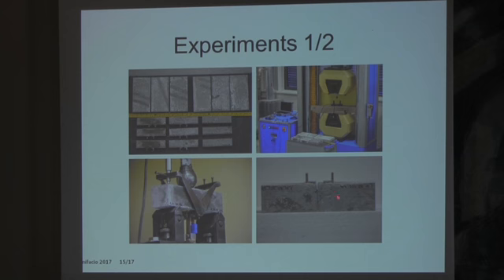Here there is the initial notch, and under the initial notch there is an inclusion. One inclusion, 80 by 8 millimeters, along the whole width and thickness of the specimen, and we now focus on crack propagation along this individual inclusion. This experiment was performed with a steel inclusion because we would like to know the behavior, and the difference between the modulus of elasticity of steel and concrete is high.